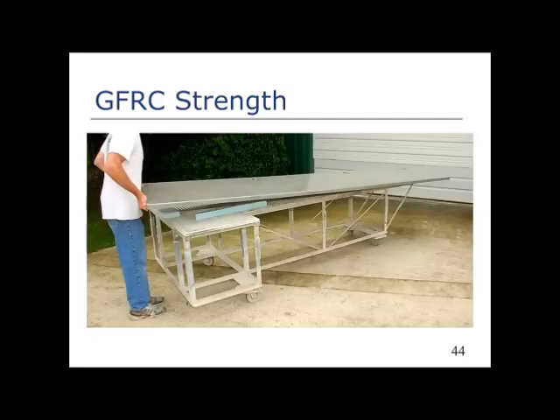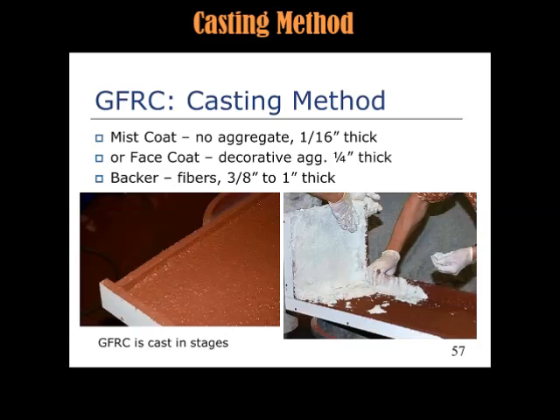Very, very durable, versatile material. So in the lower left-hand picture, you see that plum-colored or maroon-colored concrete coating the inside of the mold. That's called a mist coat. The mist coat is your basic GFRC mix design. It has no aggregate, nothing. It's just a very fine sand, roughly 0.5 millimeter in size, usually no more than 1 millimeter in diameter.